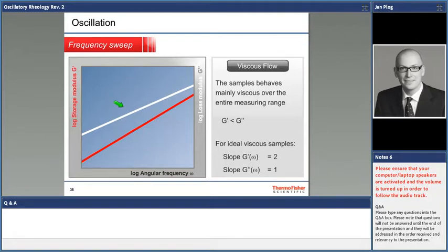Okay, which is kind of surprising, because you might think, why should a purely viscous body show an elastic response? Again, we talk time scales. When you oscillate too fast on pure water, even the water clusters, let's say, are not able to follow the motion anymore. Okay, they will stand still. Water will pretend that it's ice, and we call that dynamic glass transition. But this is only reached at extremely high speeds for a purely viscous body.